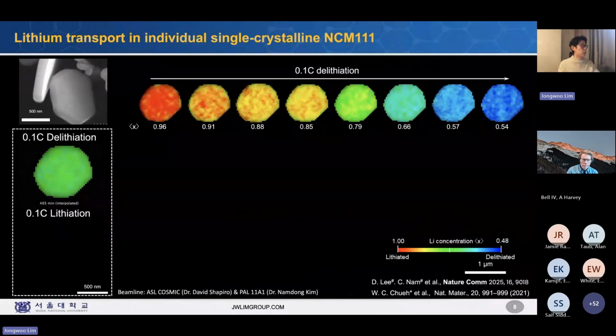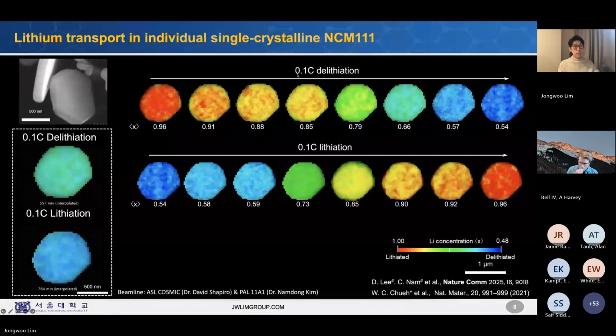One good example here is this. This is only a 500 nanometer to 1 micron particle. And Fick's law says that diffusion should be done within 5 minutes. So the diffusion time is 5 minutes. And we are cycling at 0.1C delithiation, 0.1C lithiation. So basically we apply a very small current to complete the cycling within 10 hours.